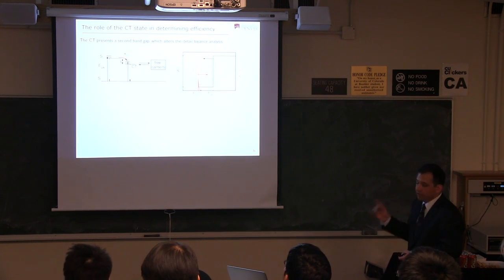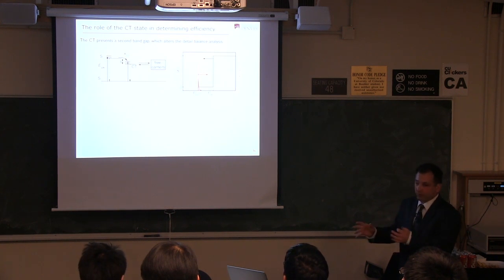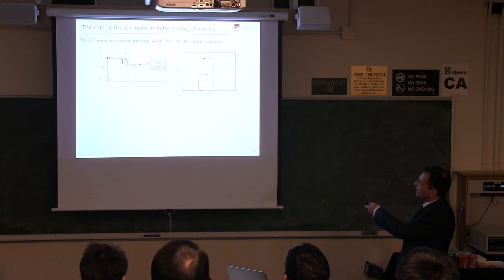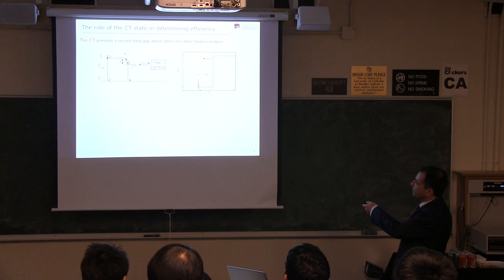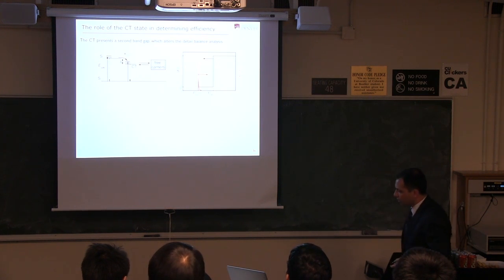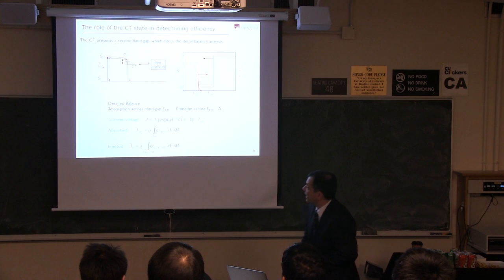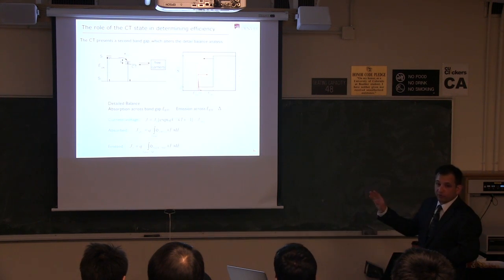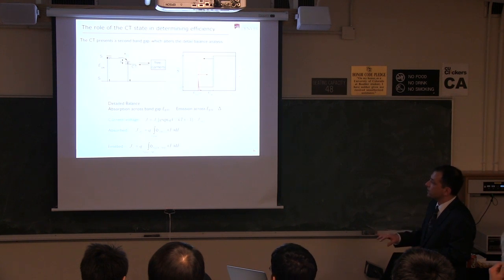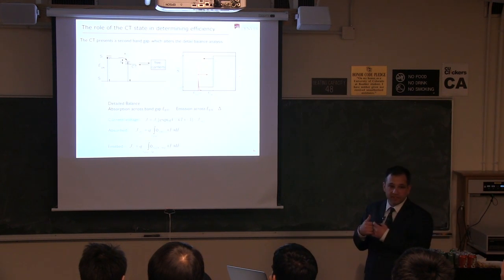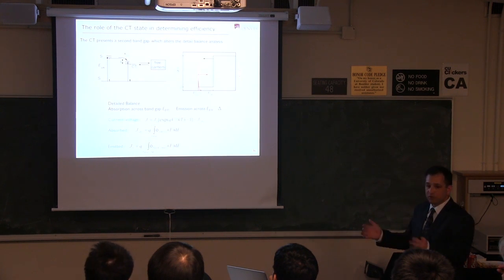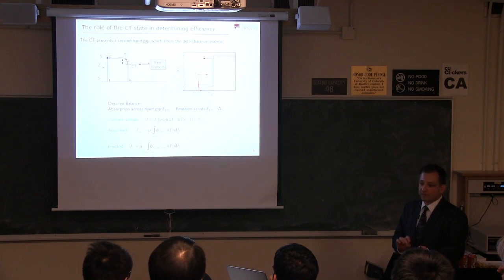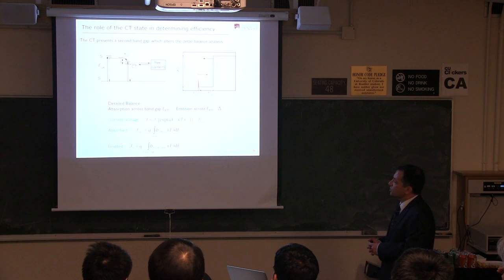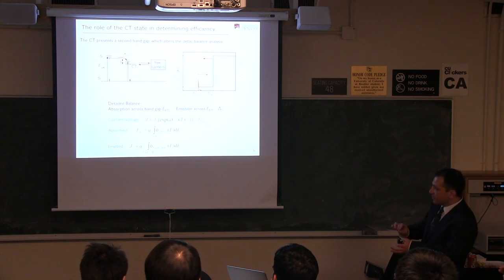So if you were to do the conventional Shockley-Queisser calculation, that's what you would do for an inorganic device, you have simply one band gap. That would be the main band gap of the material. Here we have two. We have an absorptive band gap and an emissive band gap. So when we go through calculations, if you remember the ideal photovoltaic device, how you get the maximum efficiency is that all of the emitted light, that is the black body spectrum, you assume that all of those photons came from recombination events. And that gives you the minimum possible recombination in the device. That's the black body limit. That's the thermodynamic limit.